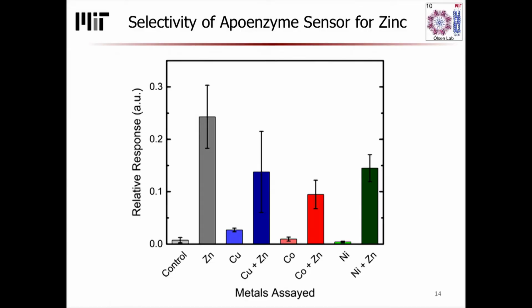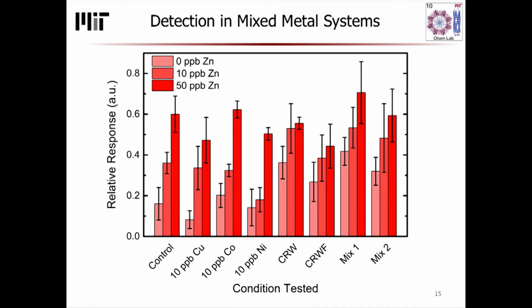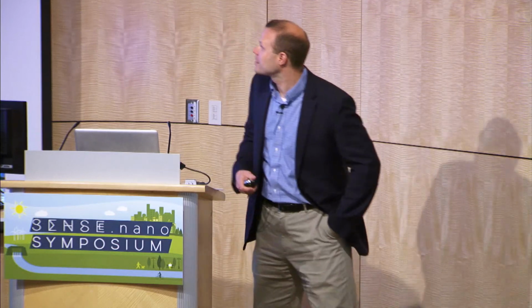The apoenzyme sensors have a very high selectivity for zinc, so the control is very low and the signal in zinc is very high. Copper, cobalt, and nickel produce very low signals, and the zinc will outcompete all of these metals in order to produce high sensing responses, even in the presence of these metals. We can do detection in mixed metal systems. So we show the control with added zinc against copper, cobalt, and nickel. CRW is Charles River water. We don't know exactly what's in that, but we can definitely detect zinc in the presence of it. This is filtered Charles River water, so we actually took the solids out before we ran the test. But it works well even in these sorts of environmental samples.